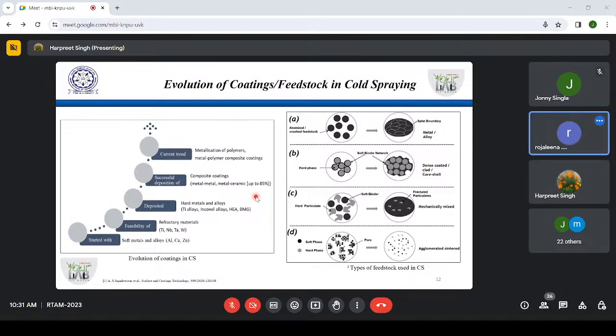Maybe. But we're using organic binders. We're using only cold pressing, that's it. The powders are cold pressed and sintered. Well, that is the best approach which you are using. You may not need cold spray actually, because that will not be the economical option for your application. So pellets by this pressing, the powder metallurgy route, is fine, not a problem. If you want to deposit it as a coating, then it makes sense actually.